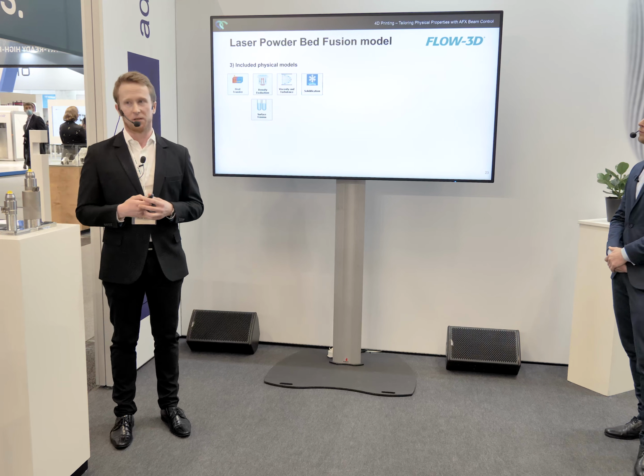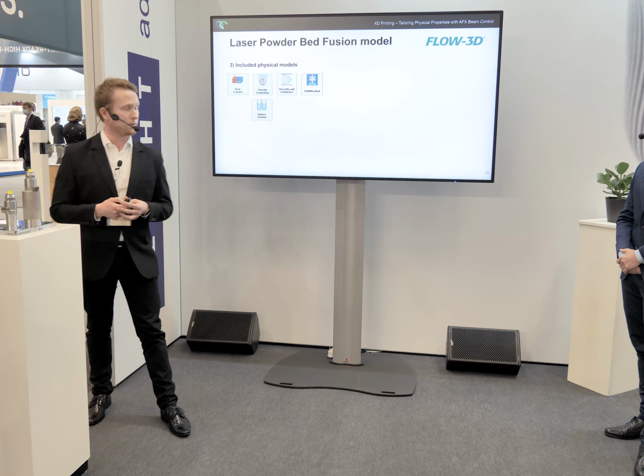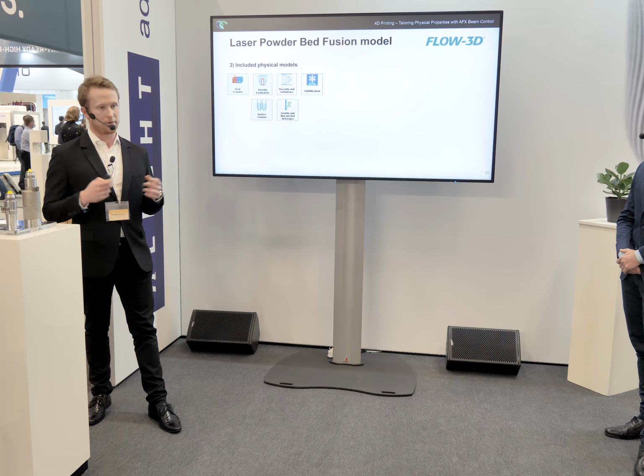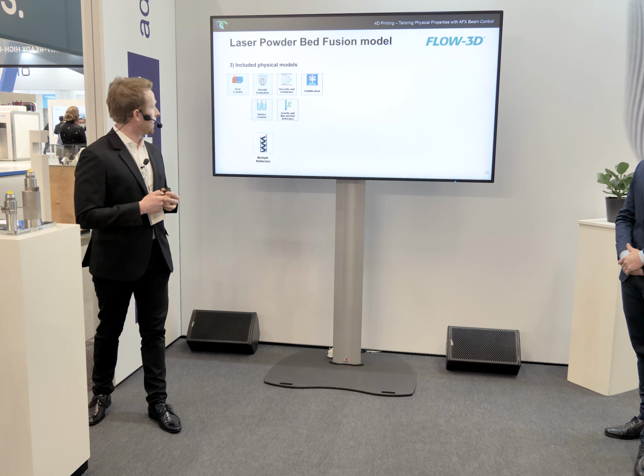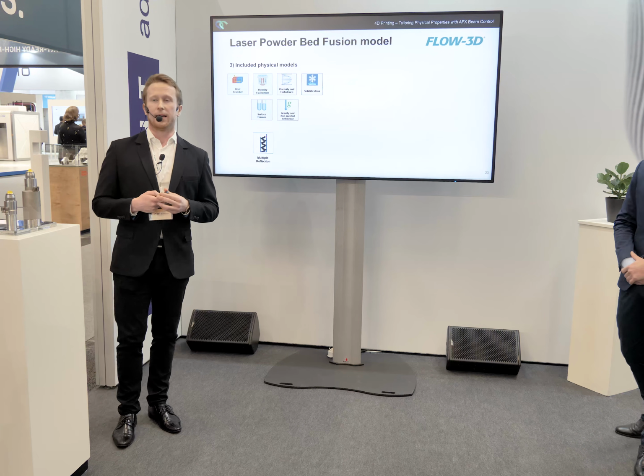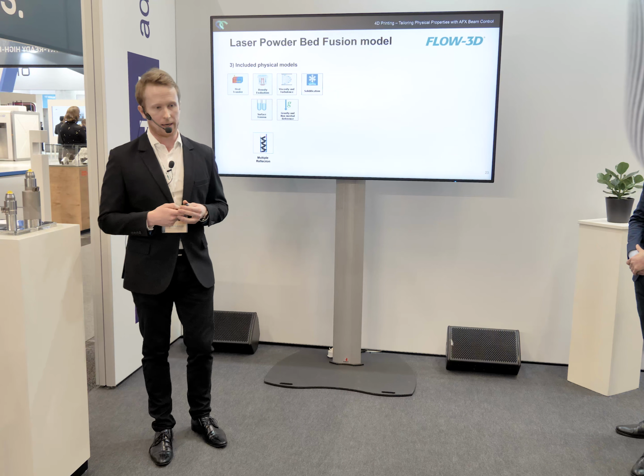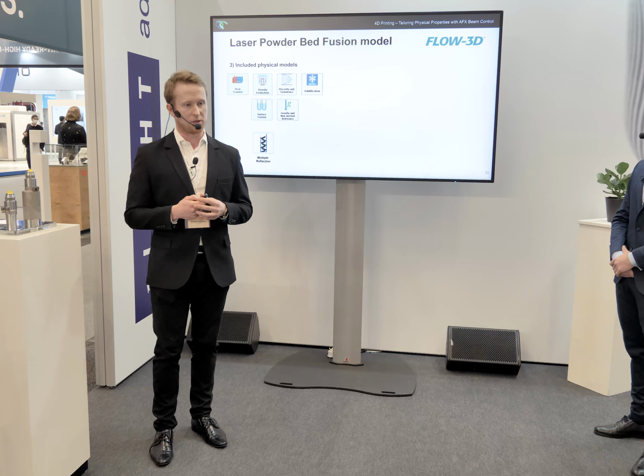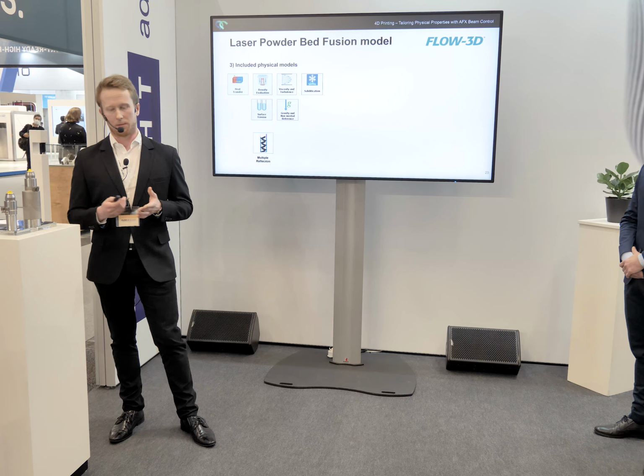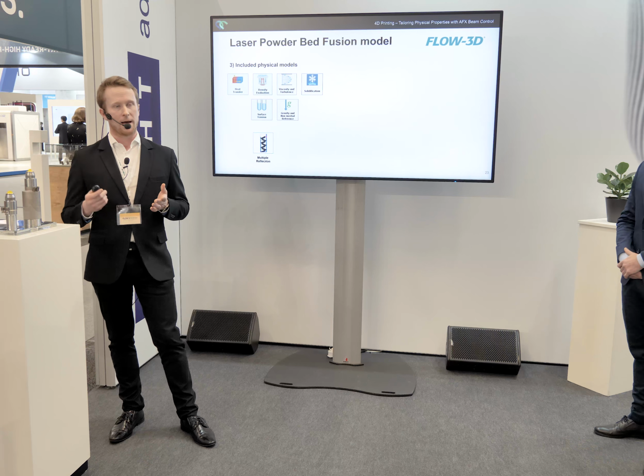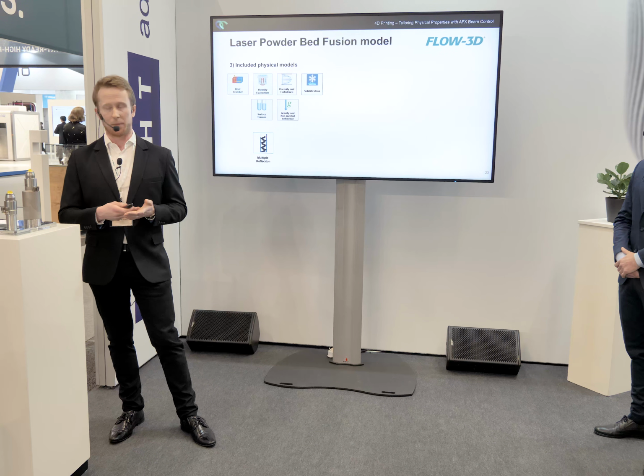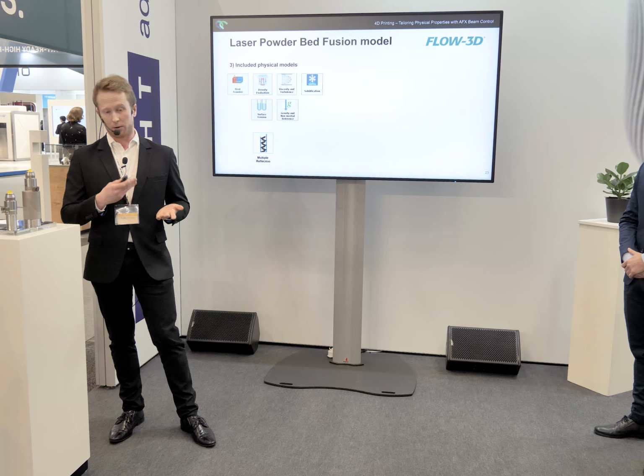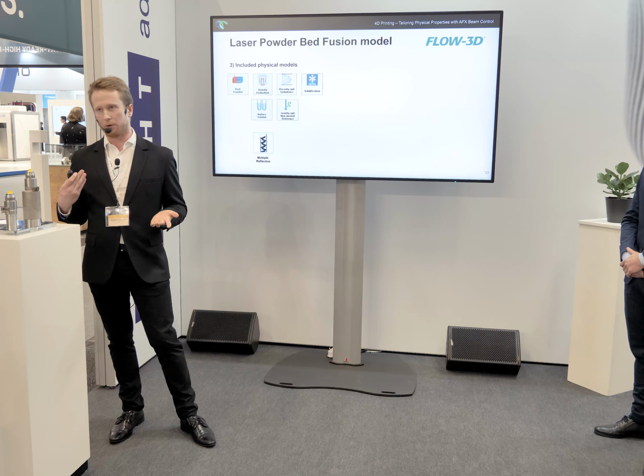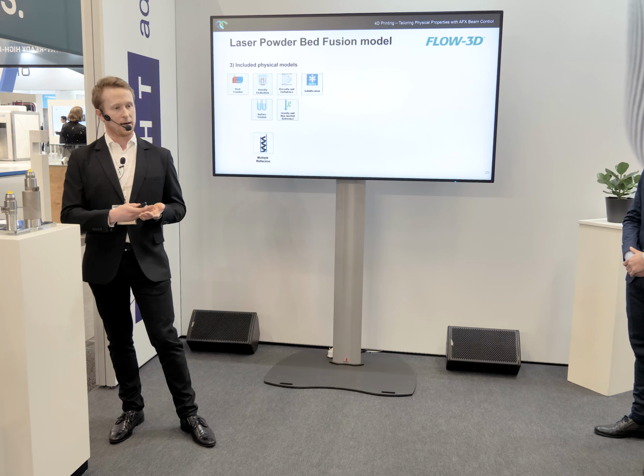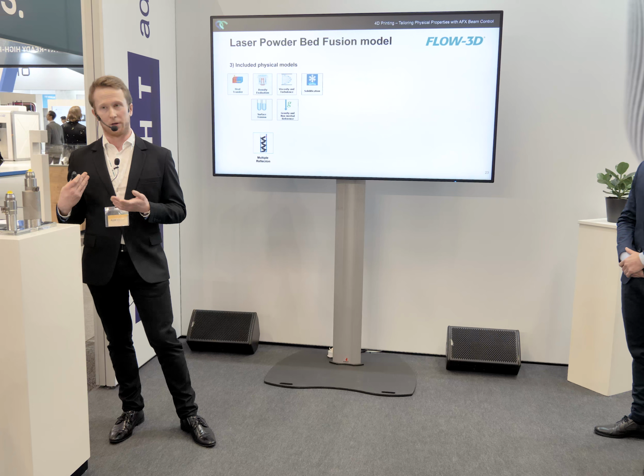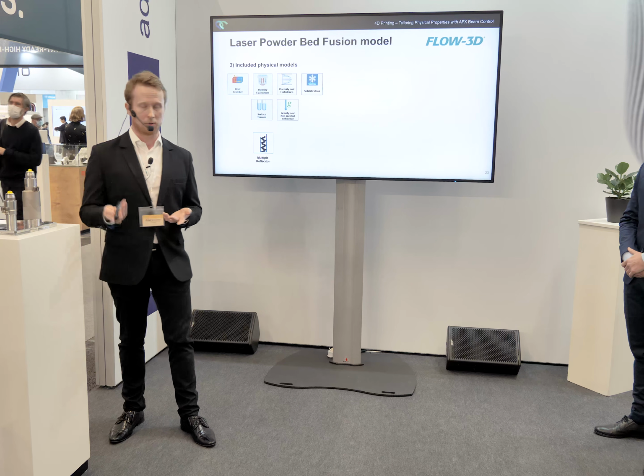The surface tension is also an important effect here in this process. And of course, we have everything in a gravitational field. On top of that, we can add the laser-specific or laser process models, such as the multiple reflection model, which is a model that accounts for the fact that if a laser ray hits the material, part of the energy is absorbed, but part of it is reflected, and it can actually hit some other fluid or a powder particle and also be absorbed there.